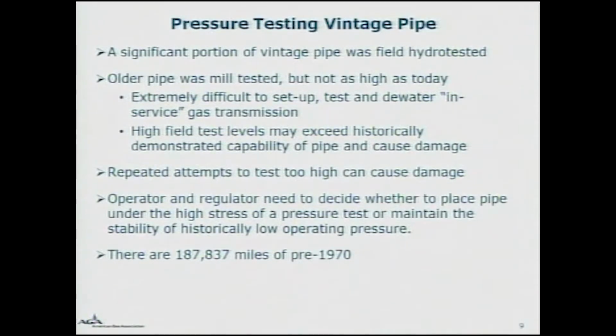While it makes sense to hydrostatically pressure test new pipelines prior to their being placed in service, if time-dependent defects can be located reliably by an inline inspection tool, utilizing the inline inspection tool is usually preferable to the hydrostatic pressure testing of an in-service pipeline. If hydrostatic testing is to be conducted to validate the serviceability of a pipeline that is suspected to contain defects that are becoming larger with time, the highest feasible test pressure should be used. The higher the test pressure, the smaller will be the defects, if any, that survive the test.